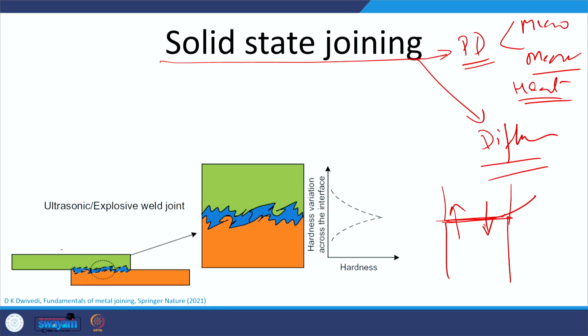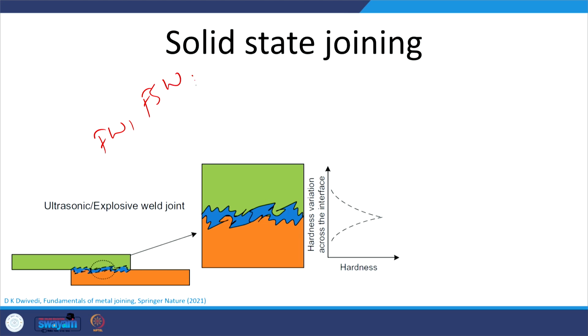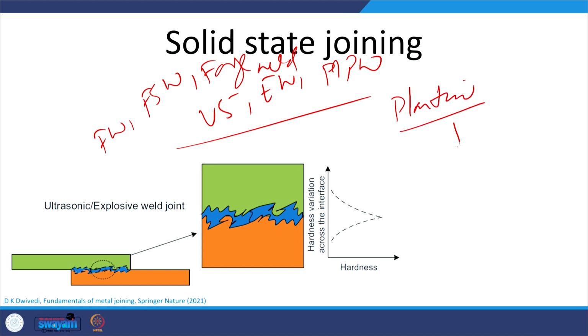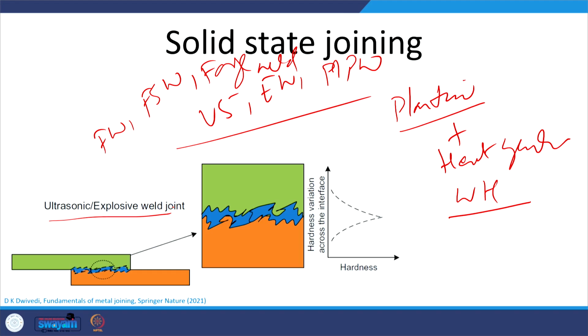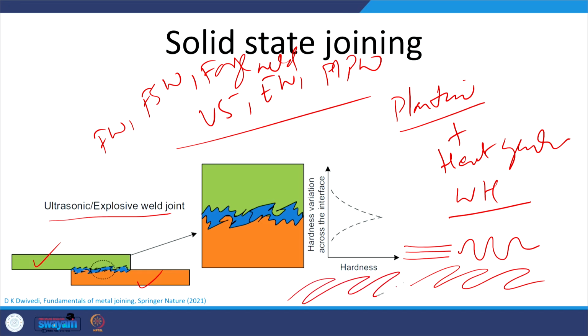So, if we talk of the processes like friction welding, friction stir welding, forge welding, okay, ultrasonic welding, explosive welding or magnetic pulse welding. In these processes certainly the plastic deformation is involved coupled with a little heat generation. Okay. So, if the metal is significantly work hardening type, then the micro level plastic deformation at the surface leads to the increased hardness. So, if we talk of, say, ultrasonic or explosive welded joints, then the two sheets being joined by the ultrasonic or explosive welding, at the interface multiple morphologies can be formed. One is simple where it is flat coupled with the micro scale plastic deformation, another is wavy structure, third is jetted, fourth is jetted coupled with the melting at the root of these jets which are being formed.